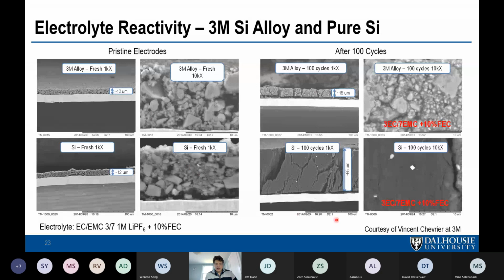So these are measurements done by Vincent Chevrier at 3M Company, and this shows you what happens when these materials react with electrolyte as a function of electrolyte additive and as a function of alloy composition. Here on the top we have a 12 micron thick coating of 3M alloy, a silicon iron-based alloy, and below it is pure silicon, also coated with the same thickness, and they look pretty much identical when freshly coated. After 100 cycles, you could see that both have gained thickness, but the silicon has expanded enormously, and you can't see any of the original particles.